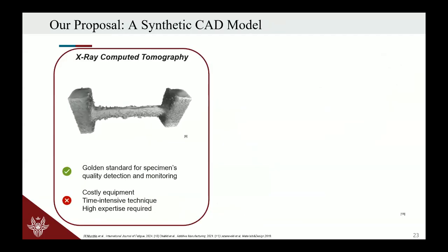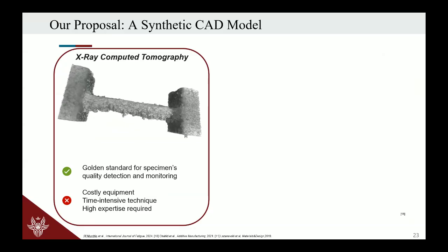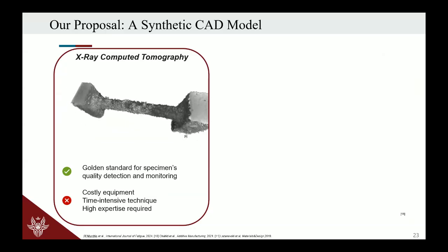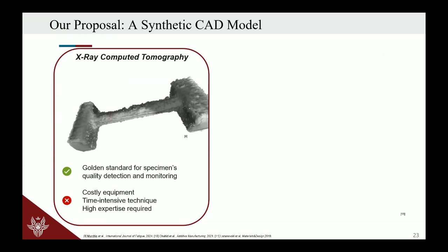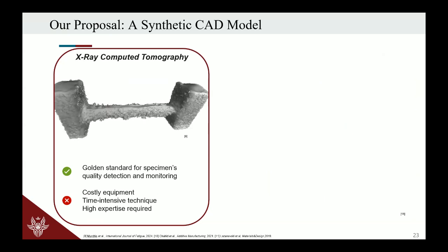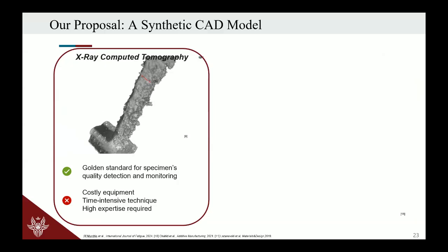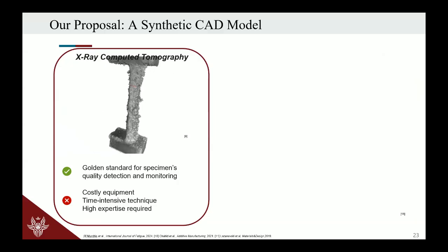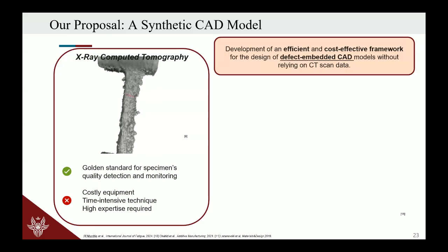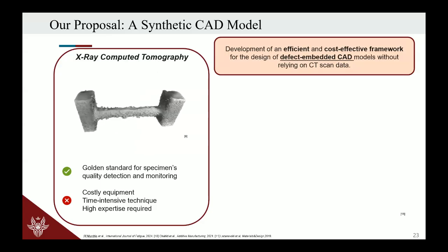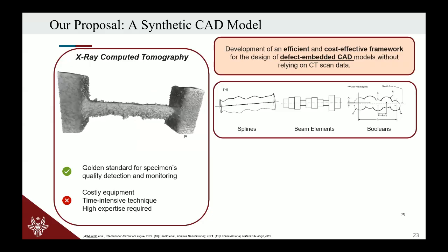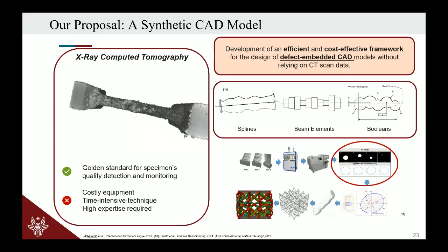So what we did was to propose a synthetic CAD model. The idea is that usually when you have to consider this kind of lattice structure, due to the fact that the surface is strongly affecting the failure, you need to have a CAD model that is able to reproduce your structure and the surface roughness, and study that from a very accurate point of view. But this is very cost expensive, and actually what we want to do is to create a simplified model.